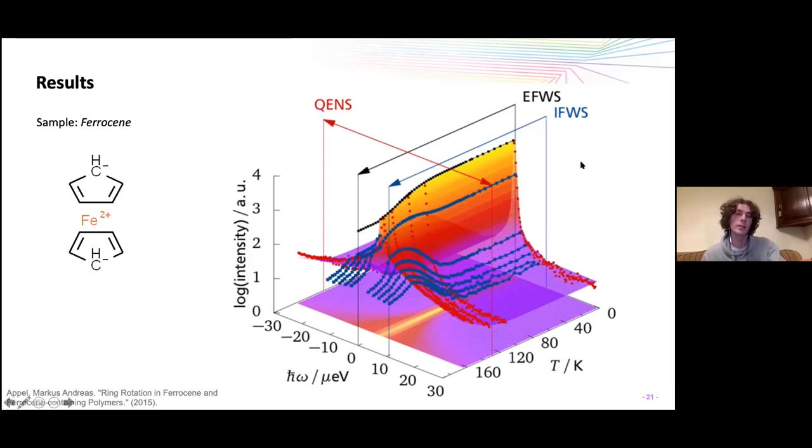Now, the IFWS is the inelastic fixed window scan. In this particular example, this is where the monochromator is moved following a rectangular velocity profile. As you can see, the temperature profile follows a continually increasing slope or ramp. The different inelastic energy transfer windows can be repeatedly cycled in order to measure all of the blue lines at once. To express that, if you take this point here at something above zero Kelvin, instead of moving first along the temperature axis, you can move along the energy axis. So you can take this point, this point, this point, and you can do all of the energies for that given temperature, then move up to the next temperature. That basically speeds everything up by a lot, which I'm going to come to in a couple of slides.